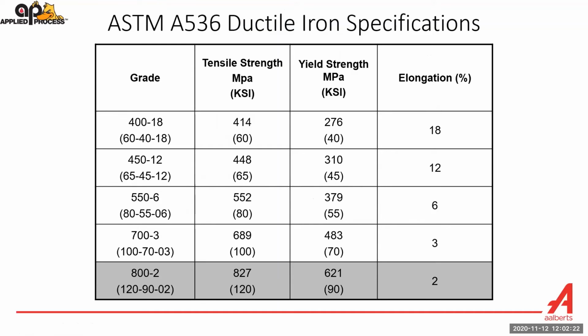This is the ASTM A536 ductile iron specifications for as cast and for quenched and tempered. And there's 60-40-18, 65-45-12, 80-55-06, 100-70-03, and 120-90-02. And I shaded the 120-90-02 because typically that is quenched and tempered to get to those mechanical properties. But as you can see, the interesting thing is, as the tensile strength increases from 60 to 65 to 80 to 100, look what happens to the elongation. It drops. So that's the amount of stretch that the material has before it breaks. And so increasing strength decreases the elongation, which is bad because you're reducing the toughness of the material.